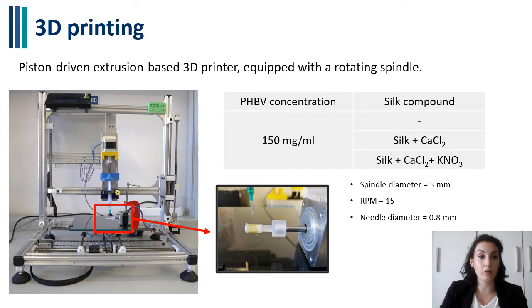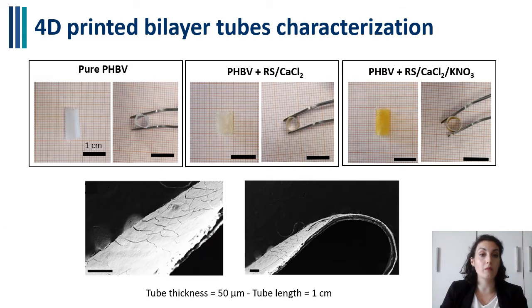The device was fabricated via extrusion-based 4D printing, equipping the printer with a rotating spindle. Here there are some photos of the developed devices with different regenerated silk compounds. Microscopic images revealed the bilayer structure of the device with a thickness of around 50 microns.